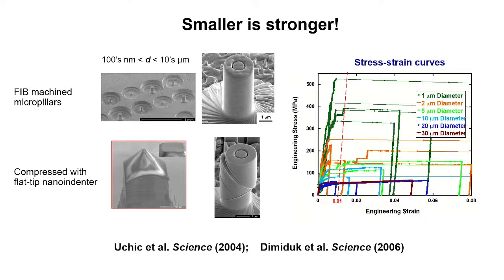The other interesting point that they noticed was that when you take the big pillars and you test many of them, the scatter in the data was very small, right? They all behave like each other because of an averaging effect. But when you looked at the small pillars, the scatter in the flow stresses was quite large. If you look at all the green curves, you'll see that the scatter in the flow stresses is quite large. So those are the two interesting things that they discovered.